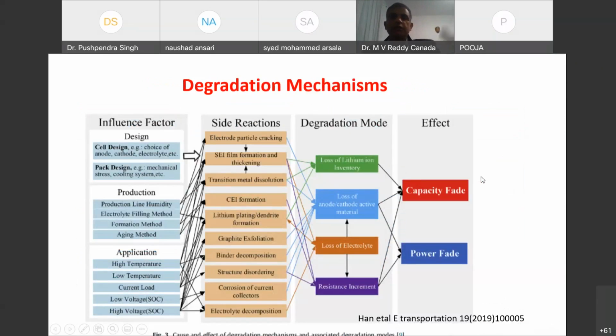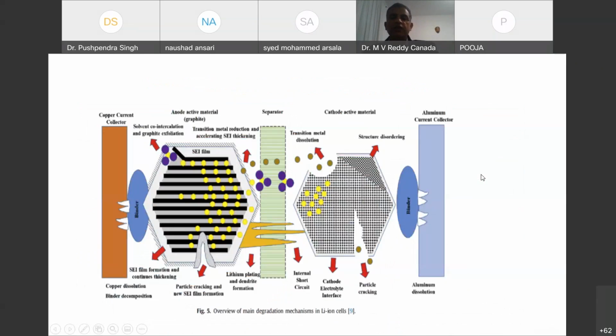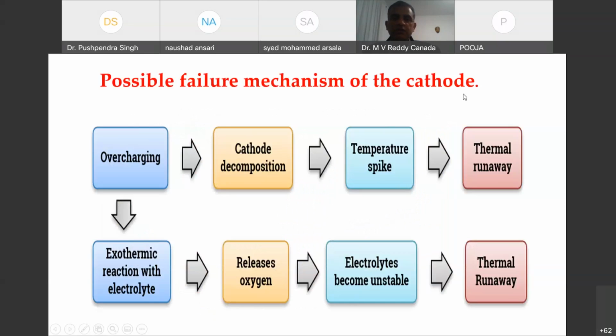So anyway, these are the same things I discussed, in different ways. If it is graphite, they call it dendrite growth. Sometimes it may puncture your separator, and you may see battery failure. In terms of the cathodes, overcharging can cause cathode decomposition, which leads to thermal runaway. Sometimes an exothermic reaction with the electrolyte also releases oxygen, which again leads to thermal runaway.